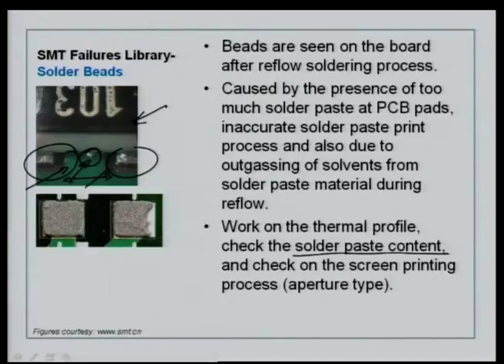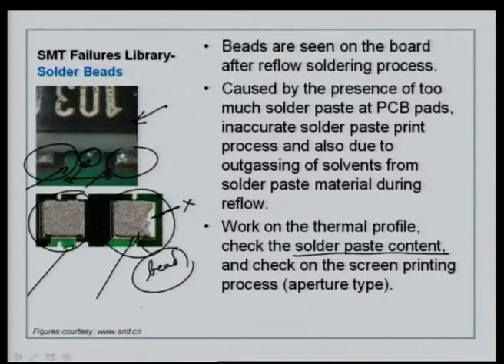So, in this case you must know what is the content in a solder paste, what kind of solvents are there, do you do gradual heating to remove the solvents, and here you can see in this picture a solder paste has been dispensed on pads, and even before attachment of the component you can see they are not adhering onto the copper pad. Okay. You can see bead formation already, because at room temperature or during tacky cure you can see that the solvents have gone and the solder paste has disintegrated.